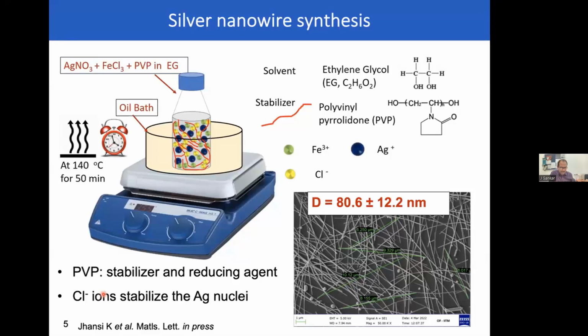Right. Thank you. And the heating application which you showed, in which you are talking about the silver nanowires, is there any change in the performance with respect to the thickness of the wire? So an individual wire is around 80 to 90 nanometers. When you say thickness, you mean thickness of the layer, right? Thickness of the wire, what we are using. So typically the wires that we grow have a diameter somewhere from 80 to 100. We don't have much control over changing the thickness.